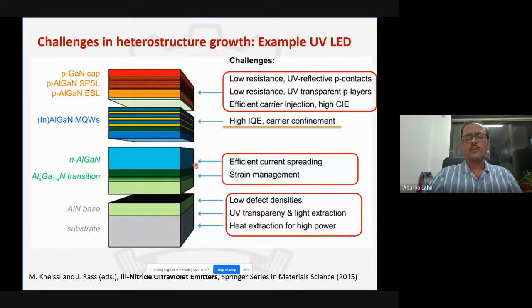And then, of course, because these materials have large band gaps, the doping also has a challenge. As such, the doping is not a challenge, but the carrier generation is very challenging, because for the dopants that are available, in order to activate them, you need very high energy. Room temperature will not help us activate those. So if you look at the numbers, for an N-type, it is okay. If you dope silicon, which is group 4, into the group 3 positions, aluminum or gallium positions, that requires an activation energy of 30 to 50 millielectron volts, which is much higher than the room temperature. So naturally, your doping or carrier generation efficiency is much lower than when you're talking about low bandgap materials. The same is true with the hole as well.